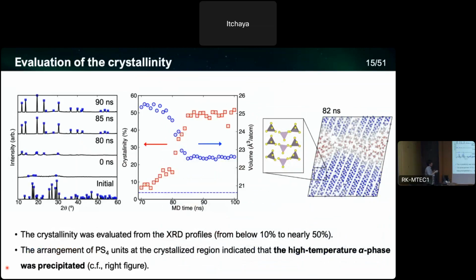So now we would like to see what is the crystallinity of the obtained structures. Then we performed X-ray diffraction simulations. These are some of the cases, and 0 nanoseconds means before the annealing, so it is the glass structure. And we seldom see peaks in the profile. But after 80 or 85 nanoseconds, some of the peaks are visible. And at 90 nanoseconds, the profile is mostly close to the crystalline structure. Then these are the crystallinity values obtained by integrating this spectrum. At the same time, the volume, the blue circles, shrinks upon crystallization.